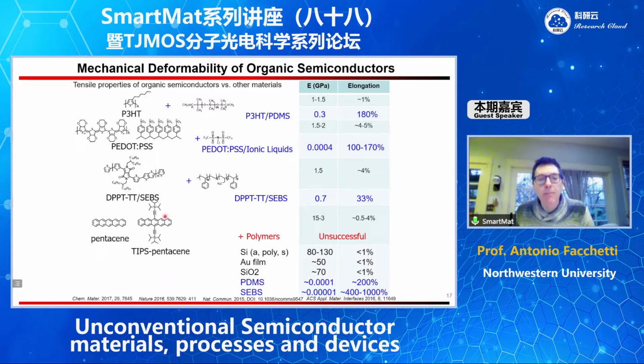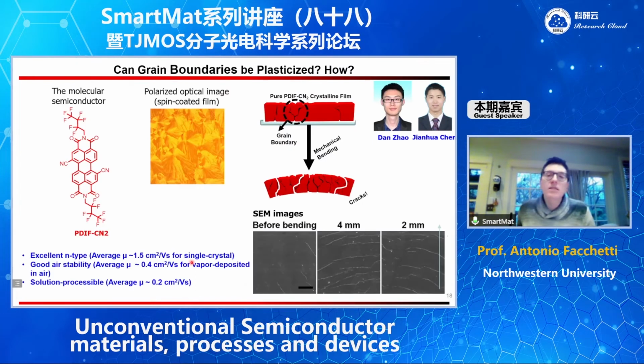However, this type of approach does not work with small molecules, and the reason is if you throw in polymers, you have a phase separation, so the small molecule does not get plasticized. So we wanted to demonstrate that instead it is possible, and we took as an example this small molecule, which we know is a polycrystalline small molecule. And if you bend this film of this small molecule on a PEN or PET substrate, it forms cracks very, very soon. So it is not an elastic material at all. It's a good N-type semiconductor, however.